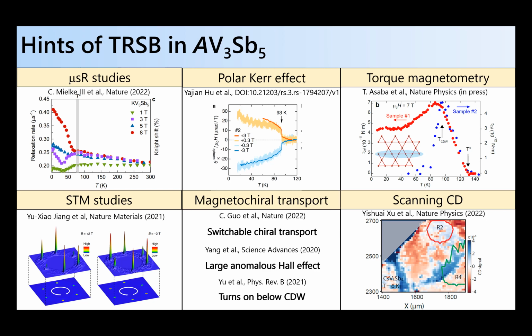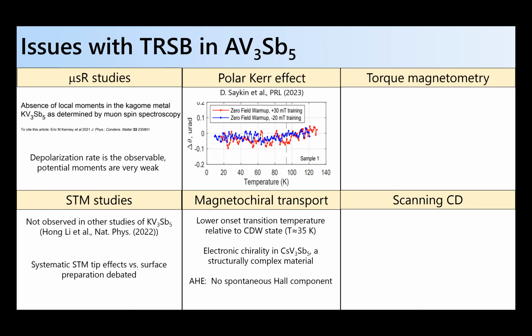But these are hints, and there are always issues with these; it's a subtle effect for a lot of these things. The most striking issue is that some experiments have been repeated on nominally the same sample by different groups, and they see different things. For the polar Kerr effect, for instance, work by Aaron Kapitulnik's group doesn't see the effect on nominally the same compound. In STM studies, there are groups that claim not to be able to repeat the original reports of switching the CDW state with an applied magnetic field. There are issues with interpreting magnetochiral transport, and some caveats, like, as we mentioned earlier, there's no spontaneous Hall component in these materials.